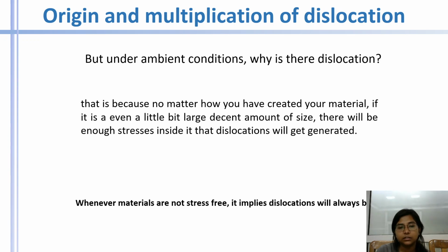But then the question is, under ambient conditions, why is there dislocation? What is the reason? That is because no matter in what way we have created our material, if it is of even a decent size, there will be enough stresses inside it that dislocations will be generated.